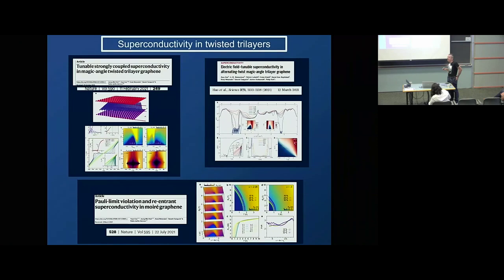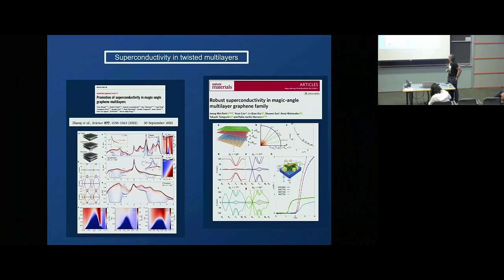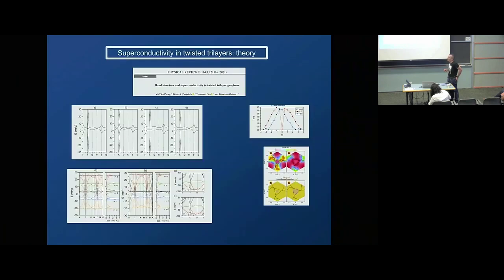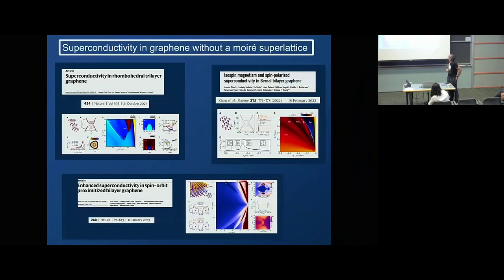Then you know that superconductivity was found in symmetric trilayers by a number of people, so we repeated our calculations for symmetric trilayers, and it was shown. As it was shown that symmetric trilayers are basically a monolayer plus a bilayer, we got superconductivity similar to the one we found for twisted bilayer graphene, same order of magnitude and everything.